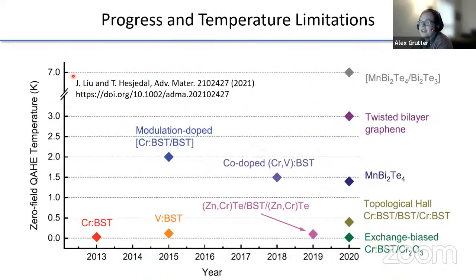And in fact, I'm looking here at another figure borrowed from the same review article that came out in 2021. You can see that the zero field quantum anomalous Hall temperature is increasing pretty quickly with time and culminated at around 7 Kelvin in superlattices of this manganese bismuth telluride and bismuth telluride. It's also been found in twisted bilayer graphene, but even so, we're still limited to 7 Kelvin, and we should be able to go higher.